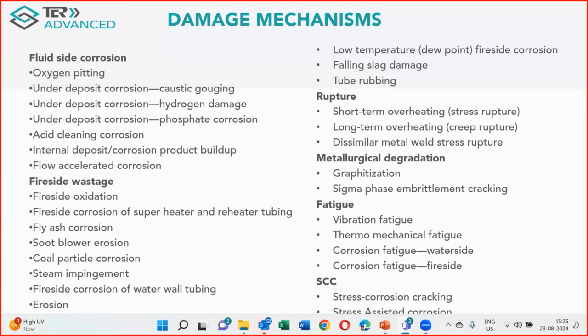Then sigma phase embrittlement is quite common in stainless steel components. In the recent past, a lot of stainless steel materials are being used in the boiler industry, where, when they are operating in the range of 550 plus skin temperature, the sigma phase forms, which reduces corrosion resistance and increases brittleness. Then you have fatigue. Fatigue is a very serious damage. Then a lot of components occur, and stress corrosion cracking and stress assisted cracking.